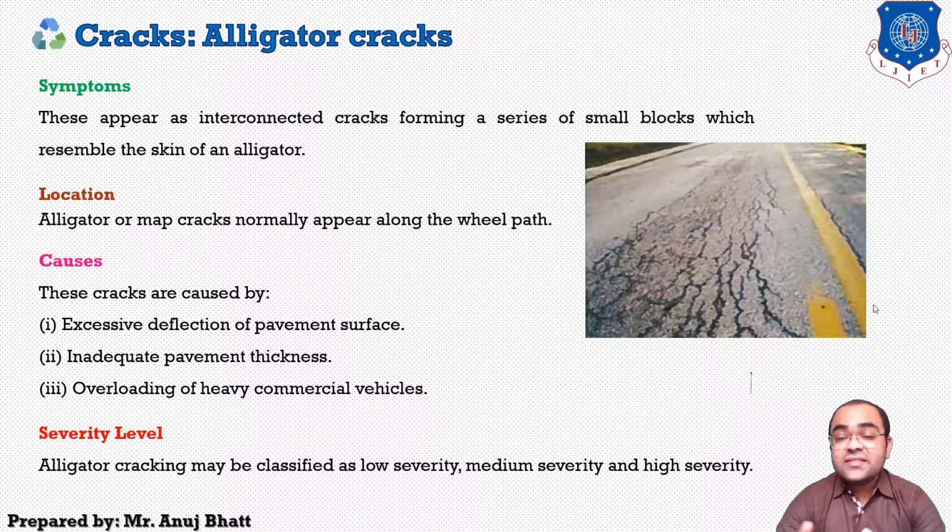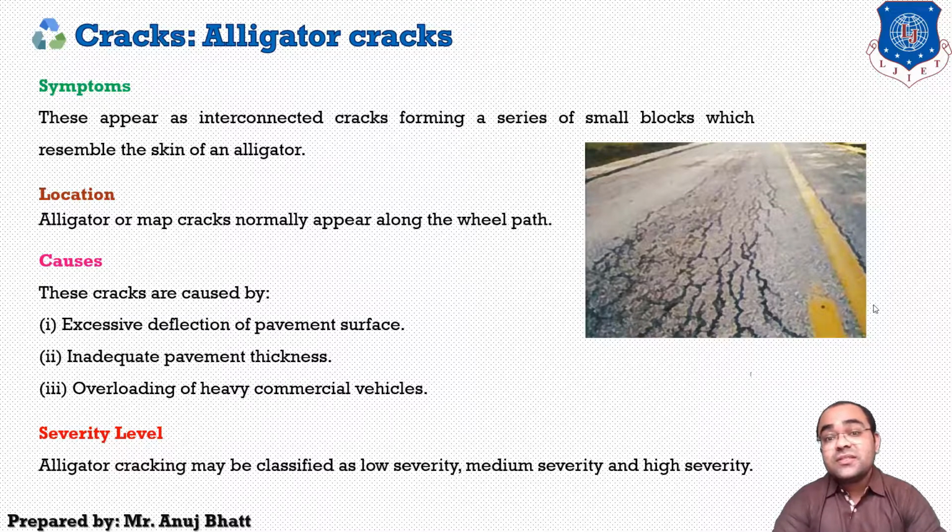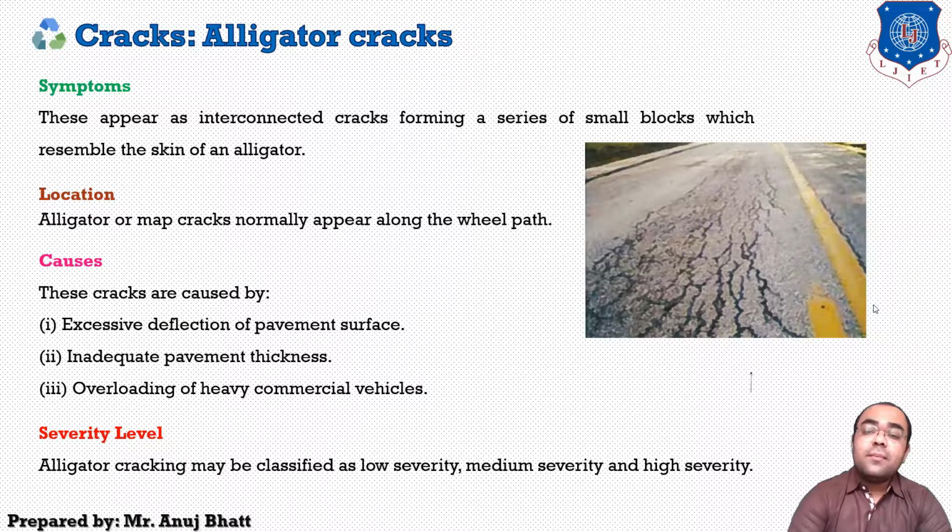In high severity, such cracks have a width and depth probably more than 6 millimeters, and pieces of the bituminous surface may be loose or missing.